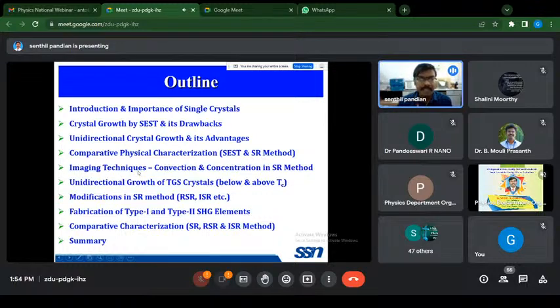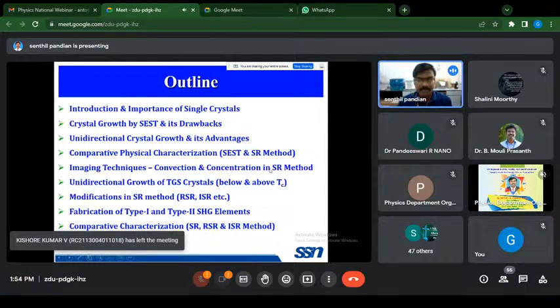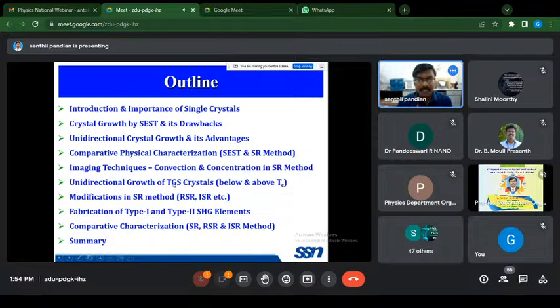We have also tried imaging techniques for identifying the convection and the concentration field in the SR method of crystal growth. And we have also tried the TGS crystal. This is a very interesting material. The phase transition of this TGS is 49 degrees. So below this 49, this material belongs to the ferroelectric nature. After this 49 degrees, this TGS crystal belongs to the paraelectric nature.